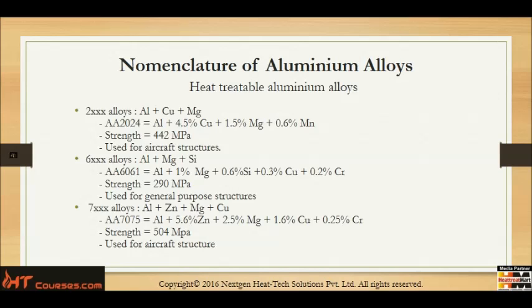The 7XXX series is aluminum plus zinc plus magnesium plus copper, translated to specification 7075, which is aluminum plus 5.6% zinc plus 2.5% magnesium, 1.6% copper and 0.25% chromium. The tensile strength now increases to approximately 504 megapascals, and it's once again used for aircraft structures.